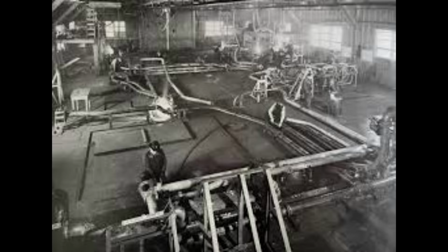52% of all serious fractures on Liberty ships originated at the corners of cargo hatches. This was not a mystery to the engineers. At the start, there was virtually no experience with welded ships, and there were built-in stress concentrations, notably at square hatch corners, at the end of bilge keels, and at cutouts in the shear strakes. These discontinuities were the origin of most serious brittle fractures.